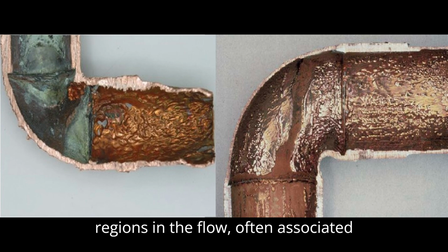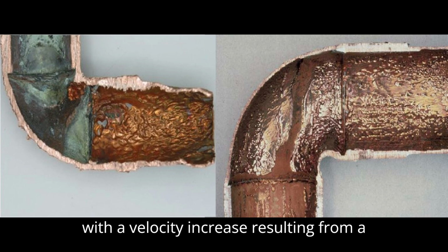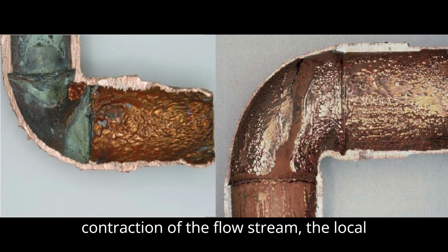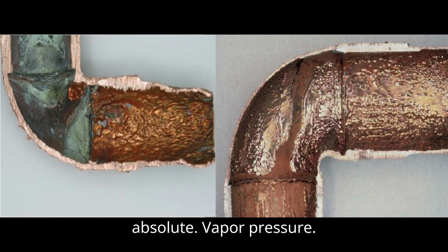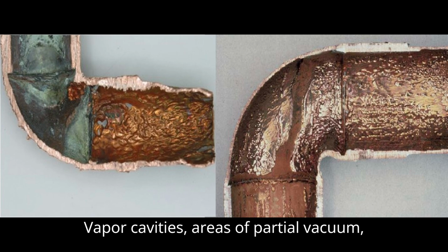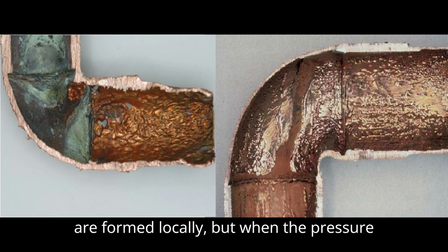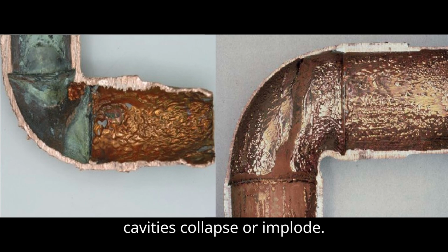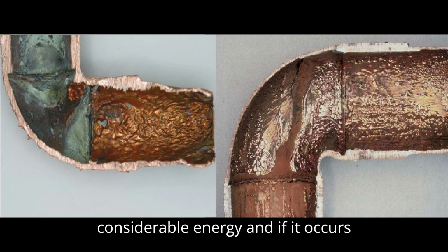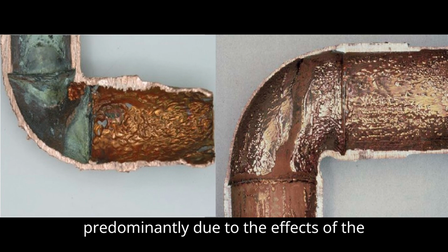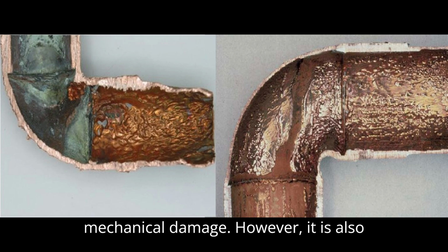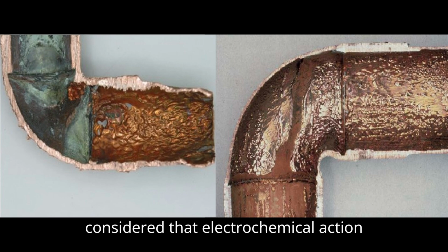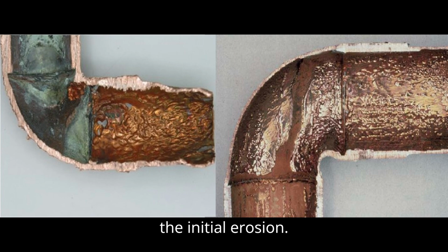At certain regions in the flow, often associated with a velocity increase resulting from a contraction of the flow stream, the local pressures drop below that of the absolute vapor pressure. Vapor cavities, areas of partial vacuum, are formed locally, but when the pressure increases clear of this region, the vapor cavities collapse or implode. This collapse occurs with the release of considerable energy, and if it occurs adjacent to a metal surface, damage results. The damage shows itself as pitting, which is thought to be predominantly due to the effects of the mechanical damage. However, it is also considered that electrochemical action may play some part in the damage after the initial erosion.